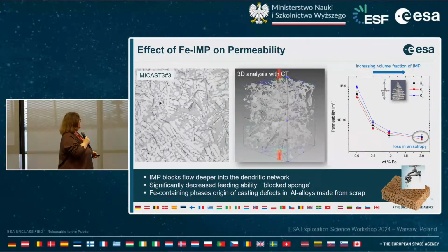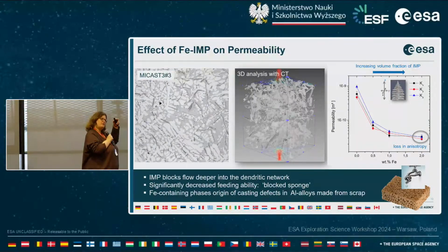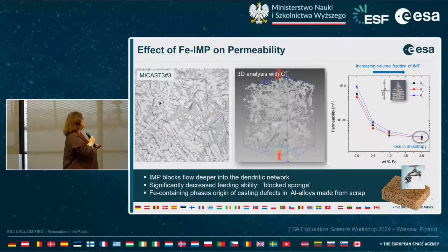So these are significantly the origin of the decreased feeding abilities in iron-containing alloys. To characterize it, we use these reconstructed cubes with a special software tool. We get some information about the so-called permeability. This means the ability of the liquid to go through such a dendritic structure. What we received is plotted here: the permeability varying with the iron content of different samples, from 0 to 2% iron. We see that with increasing iron content, and this means with increasing volume fraction of the intermetallic phases, the permeability decreases by more than an order of magnitude. All the models told me this is a really big effect, and this has to be taken into account in the models now.